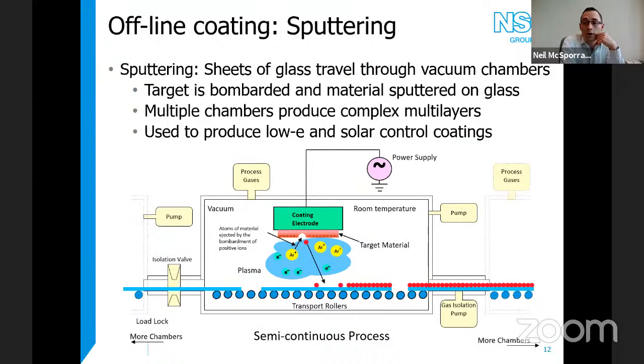The other coating technology we operate is sputtering. I'm sure everyone's quite familiar with the sputtering process. In this, we have sheets of glass, typically around 3,200 millimeters by 6,000 millimeters, so 3.2 by 6 meter size glass. We coat that in a semi-continuous process to produce both low emissivity and solar control coatings.